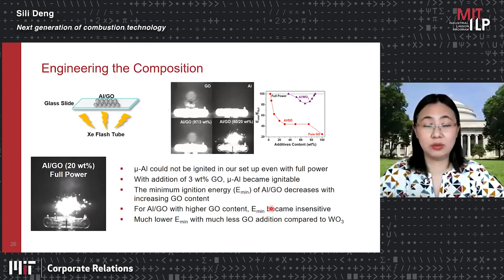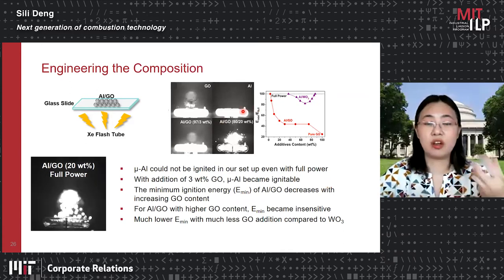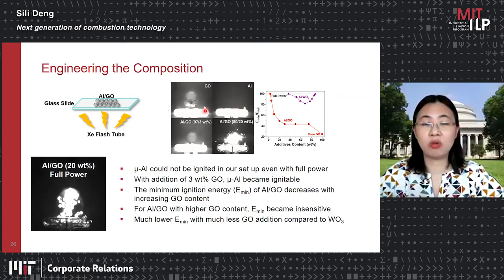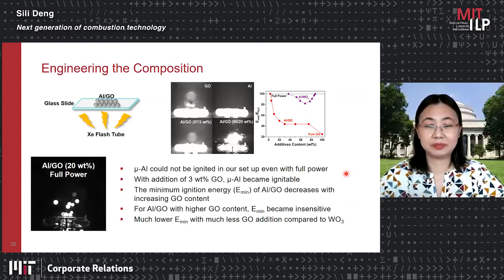Some other method is that we can add some graphene oxide particles to enhance the ignition and combustion of aluminum. As you can see, you can add almost like only 3% by weight of graphene oxide. Originally, the aluminum cannot be combusted using only the flashlight, but with only 3% of additive, you can see the ignition happens. And this is much more efficient than some other oxides that can be added to aluminum.